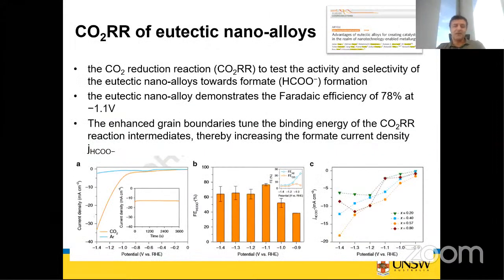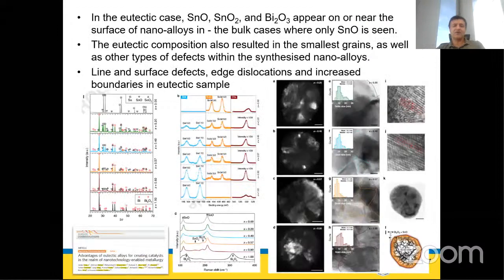So what does it mean? Here, we use those nanomaterials produced and take them for very traditional CO2 reduction reaction conversion, right? So this is for the formation of formate. We put everything, we apply the voltage. Faradaic efficiency is 78%. Voltage is actually very good at only -1.1 volt. And we realize that for most of the voltages, eutectic system has the best conversion efficiency for formate. Why? Because if you may remember, we said that we have the highest number of surface and line defects, edge dislocations, and boundaries.